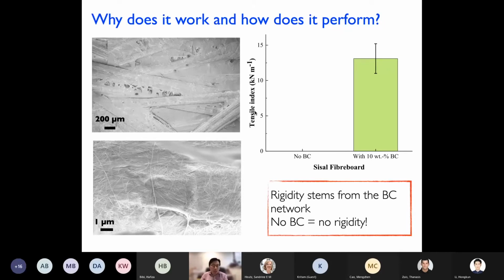In any case, without bacterial cellulose, there's no tensile index, so it doesn't sustain any tensile deformation whatsoever. With 10% bacterial cellulose, you actually achieve a tensile index of 12.5 kilonewtons per meter. So that bacterial cellulose provided rigidity to a sisal fiber preform that it never had before. So bacterial cellulose is really indeed useful, utilizing its hornification effect that binds the whole fiber network together.